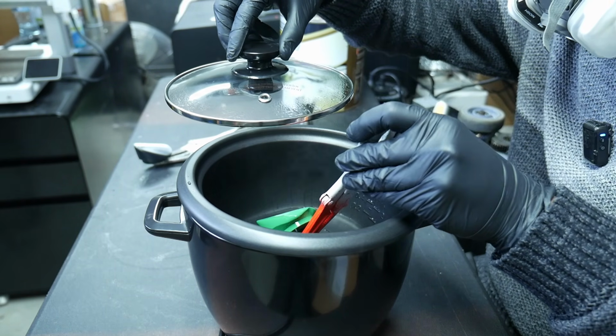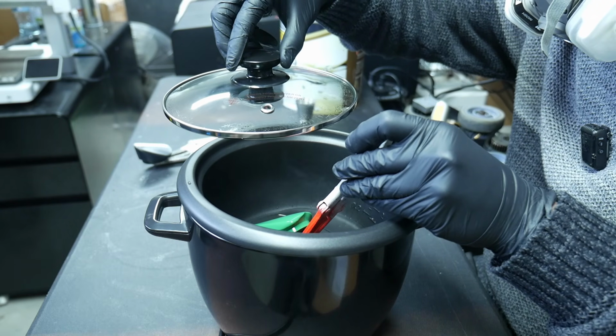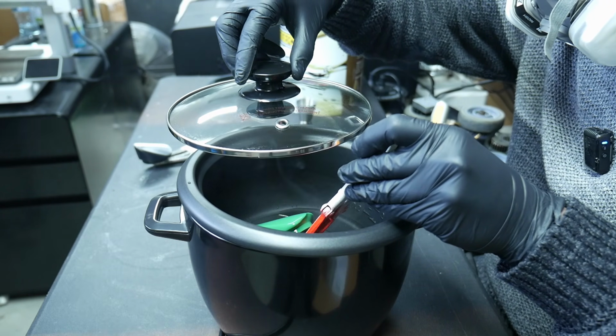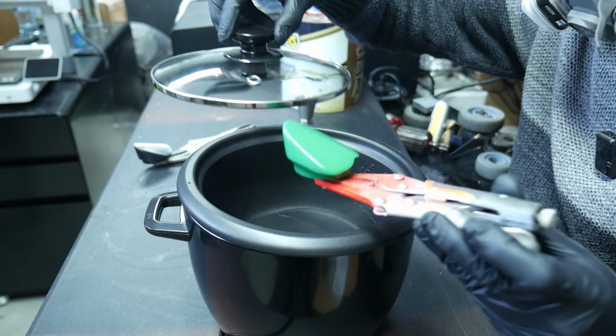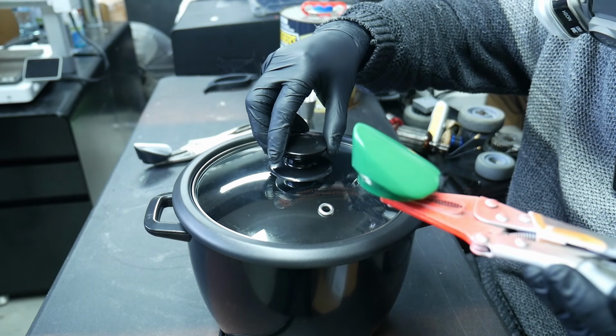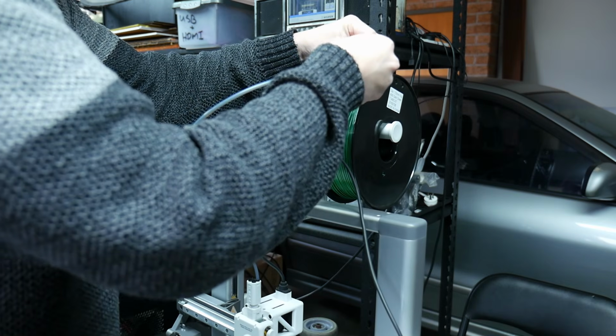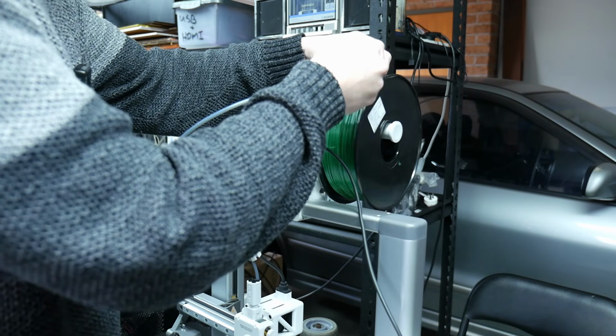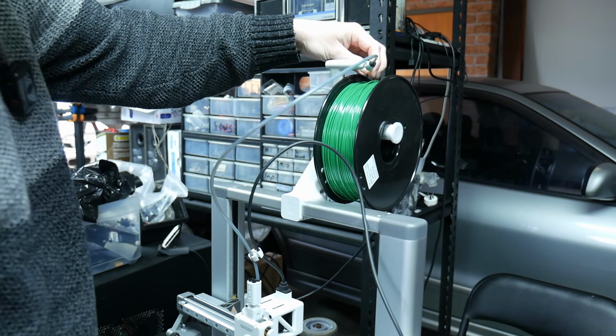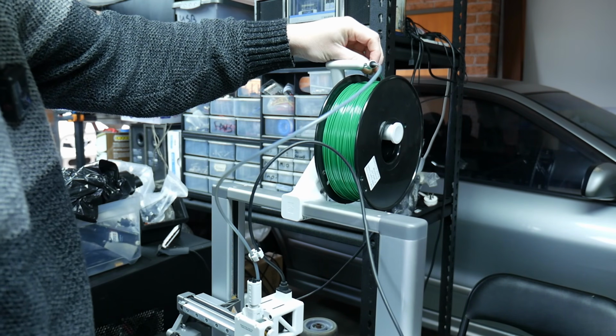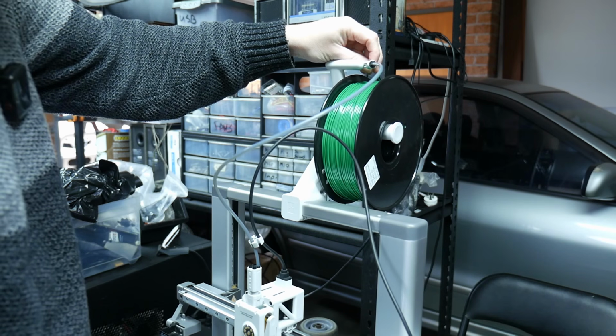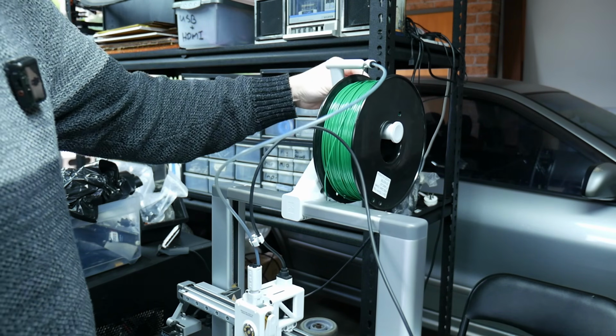Once again, you can see just how quickly the vapors coat the print, but in this case, they began to melt it immediately. It's also worth noting that this roll of ABS has been sitting open in my garage for over 7 years, and it printed perfectly fine with no issues. ABS just doesn't seem to suffer the moisture absorption issues of other filaments, so long as you keep it out of sunlight, so that's good to know.